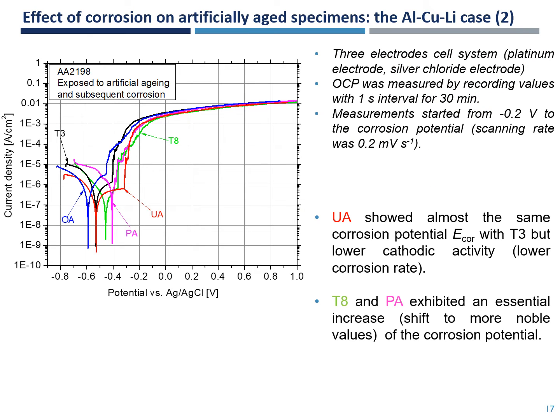The results of the potentiodynamic electrochemical measurements showed that the under-aging condition has almost the same corrosion potential with the T3, but lower cathodic activity. And the T8 and peak aging conditions exhibited an essential shift to more noble values of the corrosion potential.